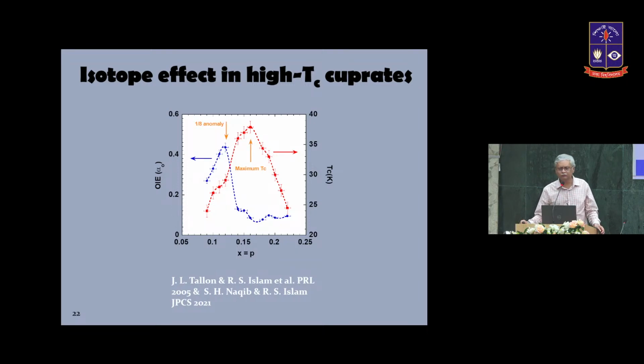When the electron boson coupling constant is strong, the isotope effect is strong, yet the superconducting TC is low. You don't expect it because, in the exponential factor, when the electron boson coupling constant is high, you automatically expect the superconducting transition temperature to be high. But you see nothing like this, especially when the TC is maximum, the isotope effect is very, very low. So what actually is happening, and that is the question I'll try to address.